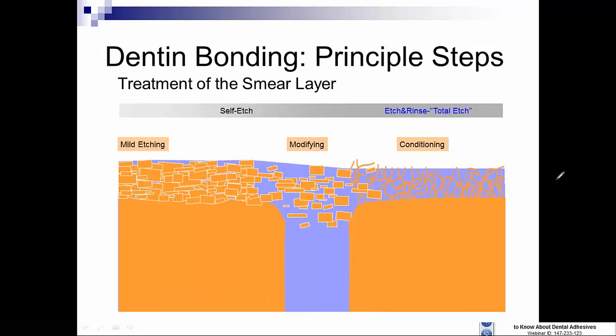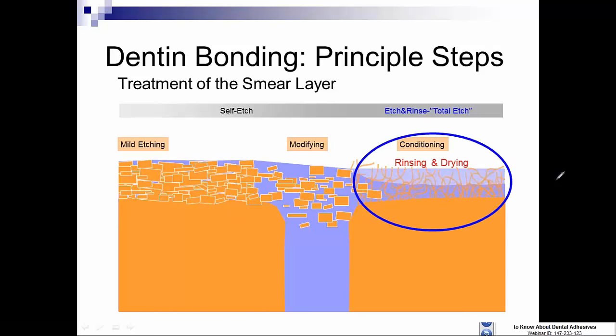So mildly etching or mildly modifying the smear layer consists of self-etching adhesive philosophies and techniques using acidic monomers in a no-rinse adhesive. Etch and rinse, or total etch, where we use phosphoric acid, again removes that smear layer completely, solubilizes a little bit of the underlying dentin, and exposes collagen. Now, one of the very important techniques for an etch and rinse total etch adhesive on dentin is, after removal of the acid, to leave a minimal amount of moisture in the collagen to prevent the collagen from collapsing.